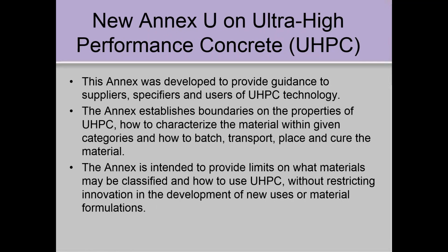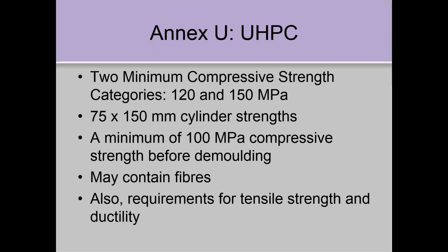Okay. Now the other new annex is on ultra high performance concrete, which has been, as I said, hitting the industry. And that's not a huge impact at this point, but it's growing. And it discusses how to deal with it because it's a completely different type of concrete. So it provides information on what's considered ultra high performance. As I mentioned earlier, there's two minimum strength classes, 120 and 150 MPa. These are tested on even smaller cylinders, 75 by 150 cylinders, because it's so strong that testing in a regular testing machine would be difficult.